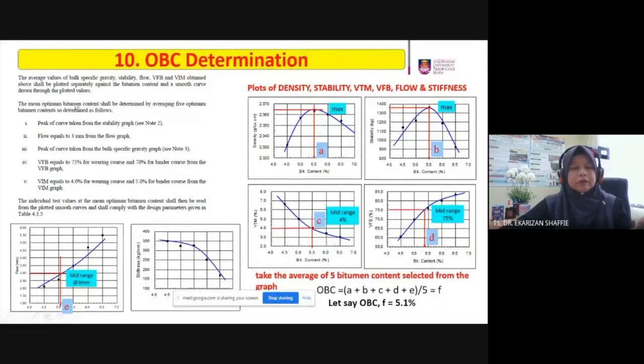For example, this is from the JKR specification. In order to determine the OBC, we have to select the peak of the curve taken from maximum density, which we denote as A, and the peak of the curve from stability, which we denote as B. For VTM, if you look at this standard, VTM or VIM is equal to 4%. We just consider it as the mid-range, so 4% mid-range, which we denote as C.